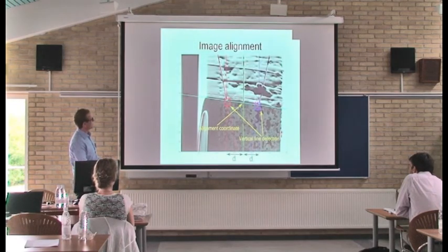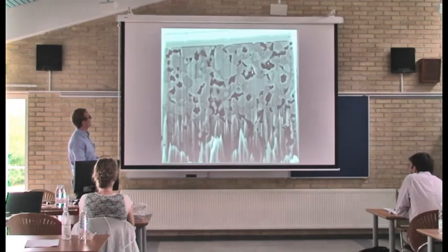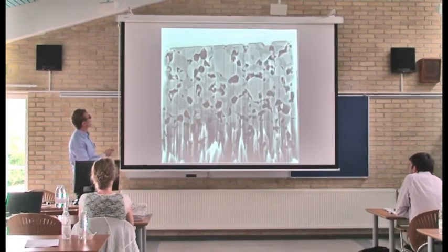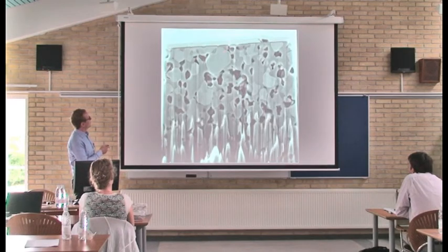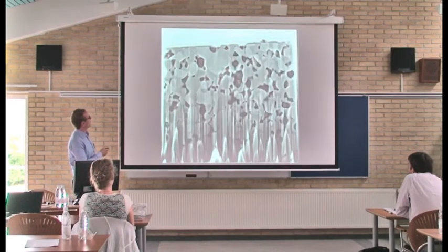To do this, we do a very simple line detection, where we detect fiducial line markers in the protective layer deposited on top of the sample. By detecting this center line and also the underline of the protective layer, we can obtain an intersection point on each of the frames. We can then use this point to align all our image data. You can see here, in this modified sequence, that the point used for the alignment is now stationary throughout the sequence.